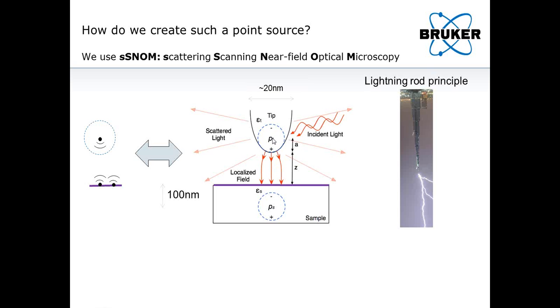Now, because the center of the dipole is inside the tip, the closest you can get is about the tip radius. But that's still pretty good because the tip radius can be made as small as 10 nanometers. So you can get within 10 nanometers of the sample surface, giving you access to about 5 nanometers of resolution, potentially.